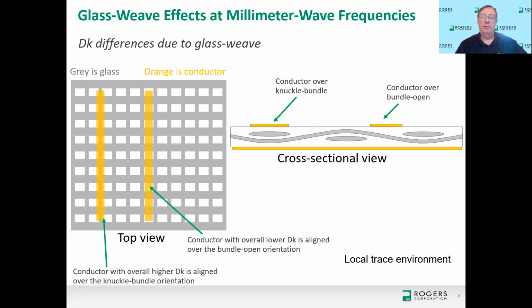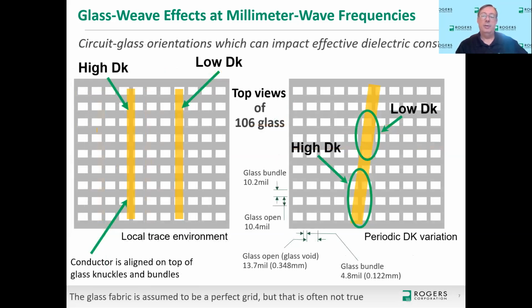That same type of concept can be shown to the right in a cross-sectional view. And then moving on, there's multiple ways to think about how the glass weave pattern can interact with the circuit. However, these are the two most common. On the left is the local trace environment, and on the right is the periodic Dk variation. And the local trace environment, we already talked about some, and that is when you have a signal conductor that's aligned to the knuckle bundle area, that is going to perceive a higher dielectric constant overall as compared to a neighboring circuit with a signal conductor over the bundle open area that's going to have a lower dielectric constant.